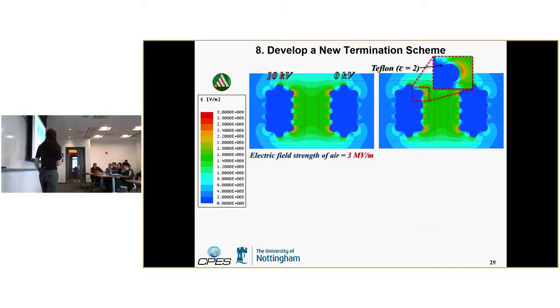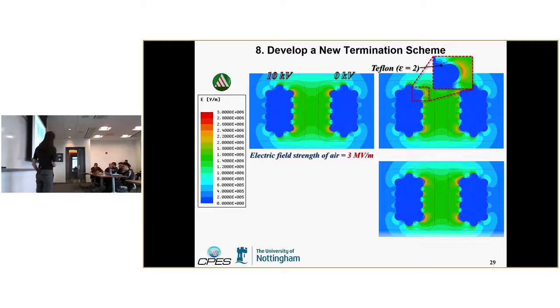Okay, so what if you coat these springs with a dielectric material? If you use something like Teflon that has a low permittivity close to that of air, then you can get some reduction in the electric field in the air. But you need to be careful. If you use a dielectric such as silicone with a higher permittivity, then it has almost no impact, because it's not going to drop a lot of the electric field over that. The electric field will go mostly in the air because of the higher permittivity.